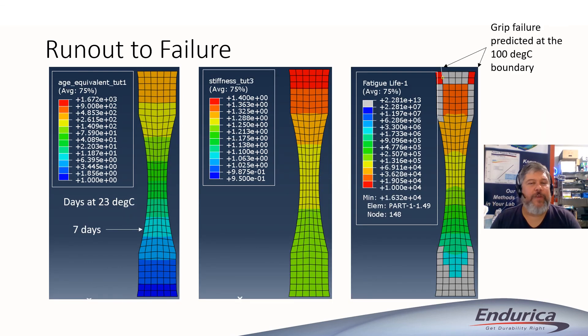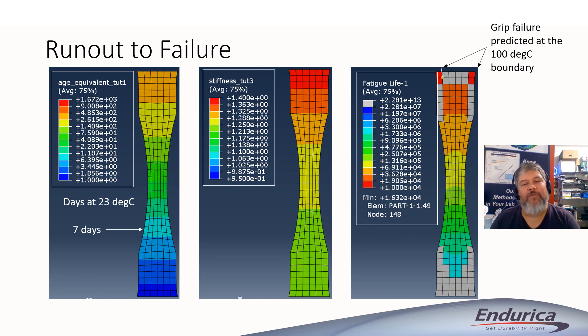In the aging workflow, both the stiffness and the crack growth properties depend on time. Endurica DT uses a co-simulation workflow that couples with Abaqus to update stress and strain fields as stiffness evolves during the problem. What you're looking at on this slide are the distributions of, on the left-hand side, equivalent age on the master curve. In the middle, you're looking at the final stiffness distribution at the end of fatigue life on the part. You can see that at the top grip we've achieved the highest amount of equivalent exposure time, because that's the hot end of the specimen. And on the right, we're showing the computed fatigue life taking into account aging on the specimen.